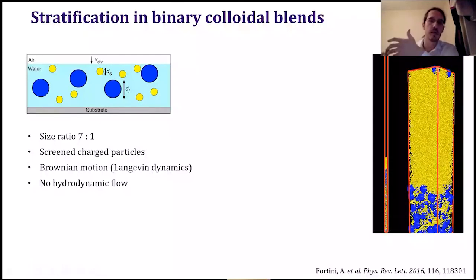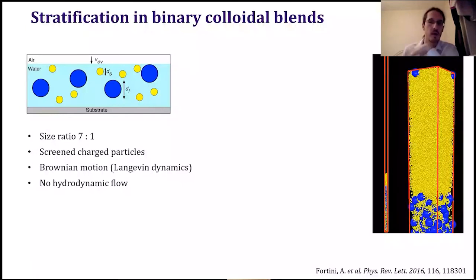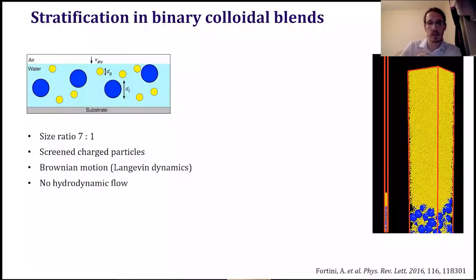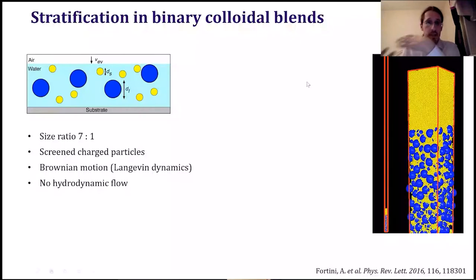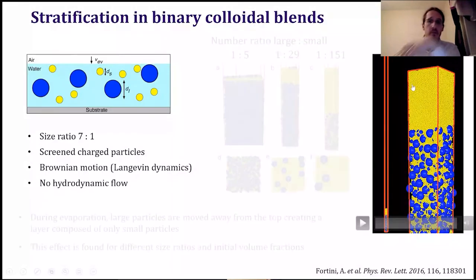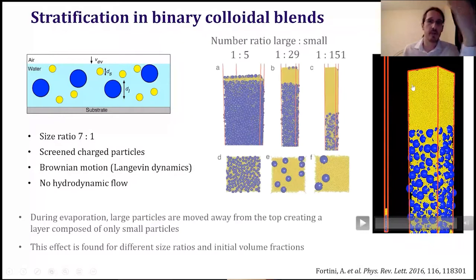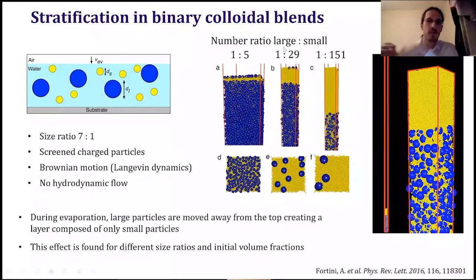So you just blend them in a dispersion, dry them, and then you end up with a coating which has the small particles at the top. And this seems to be quite reproducible for different number ratios, meaning the amount of large versus the amount of small particles, and also the size ratio between the two particles. But obviously this is simulation, and in simulation everything was perfectly fine, and in experiments this is a bit more tricky, but still the idea is really good of having a system where you can control the small particles to go to the top, and then if you want, you have a functionality.